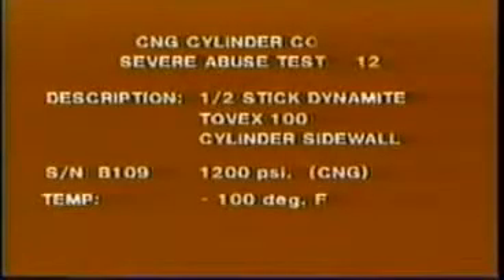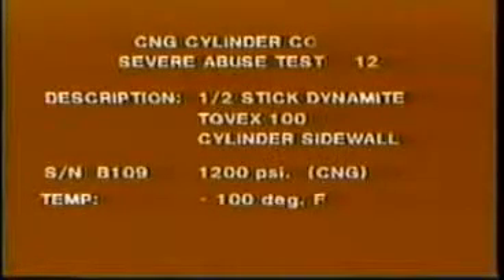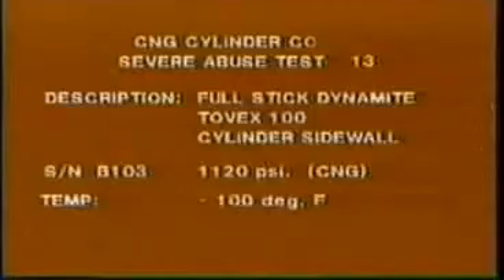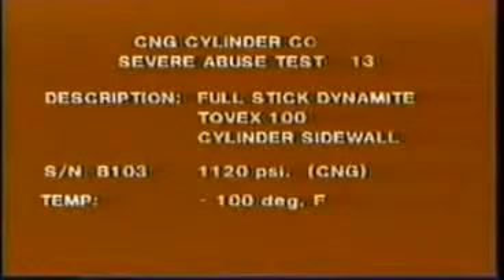These low temperature tests point to another advantage of these cylinders. Aluminum increases in both strength and ductility at low temperatures, whereas the embrittlement temperature of carbon steel is approximately minus 65 degrees Fahrenheit. This is particularly the concern for motor vehicles operating in northern latitudes, such as Edmonton and Alberta, Canada, and Alaska. And again, at a full stick and extreme low temperatures, the cylinders stayed intact and the gas did not vent.